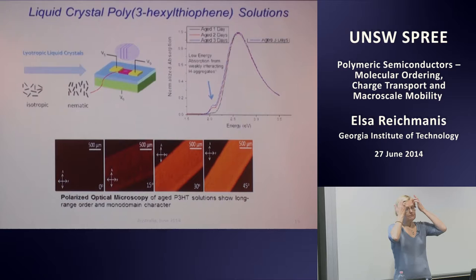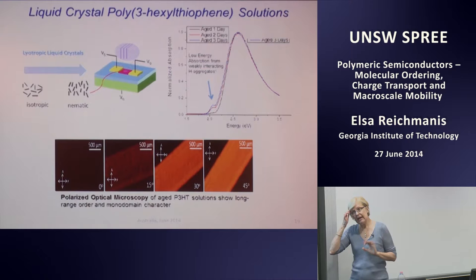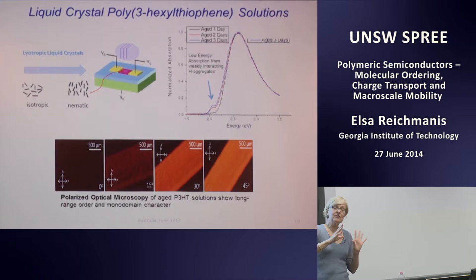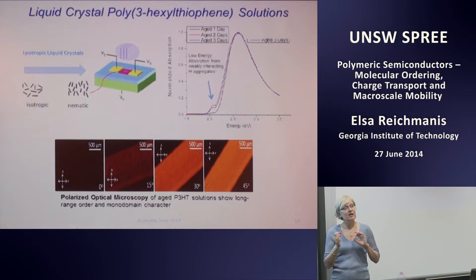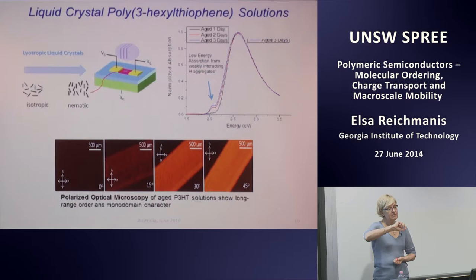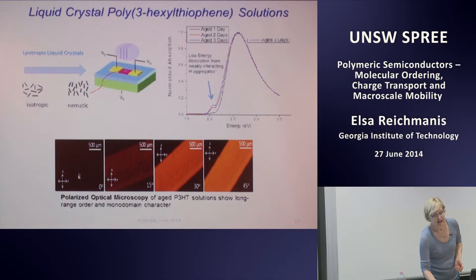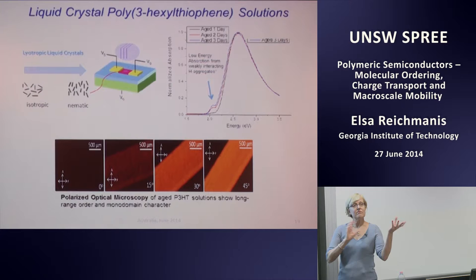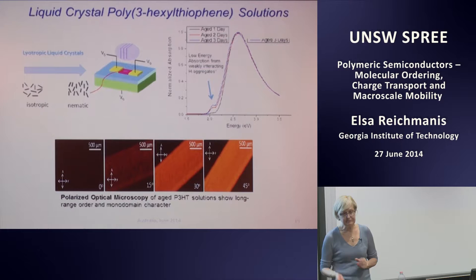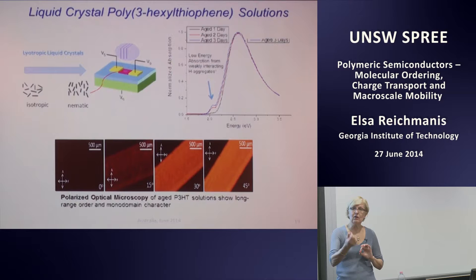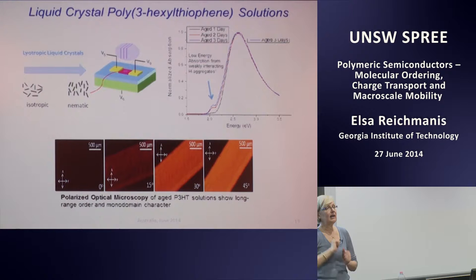We're looking at that now, and these are preliminary results, and there are some results that we'd like to try to reproduce. We were able to make very concentrated solutions of poly-3-hexylthiophene and draw them into a capillary. From the UV spectra and the polarized optical microscopic images, the P3HT that's been drawn into a capillary exhibits birefringence and long range order along with monodomain character. We're consistently able to generate the monodomain samples.